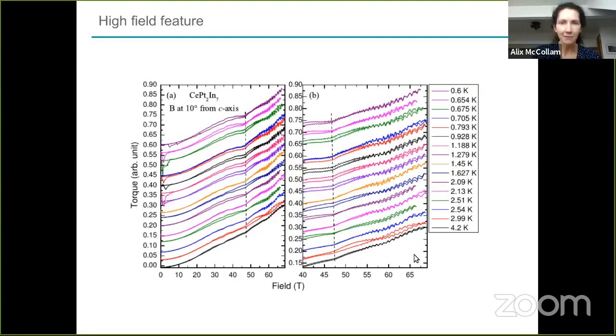Then the very last thing, in the last minute that I will steal from the question time. These are the torque data as a function of field up to the maximum field. These data are in the PhD thesis of Matthias Rabe. I think I have the reference maybe on the next slide. But this is a clear feature at around 45 Tesla. So this is as a function of temperature. All of the different colors are different temperatures given here. This one is the highest temperature, but it doesn't move very much.